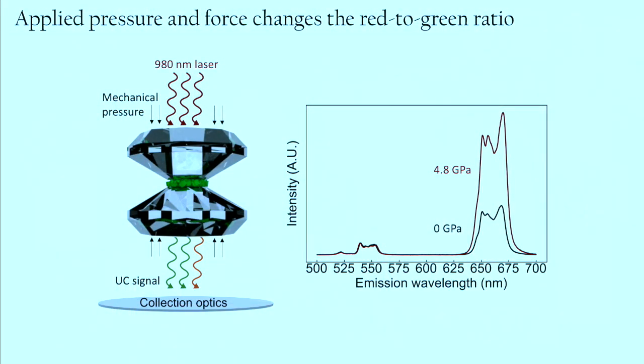We characterize their force sensitivity by using atomic force microscopy and also diamond anvil cells. So some of you may have done this technique before. We essentially have two diamonds that we use to press on our nanoparticles. The diamonds are transparent, so it gives us optical access to the nanomaterials, and then we can characterize their upconversion emission. And you can see as we go from high pressure to low pressure, there's a pretty significant change in the spectral response. So this is the upconversion intensity. You can see there are peaks right around 520 or so nanometers and 550 nanometers, that's in the green, and then there are peaks in the red.